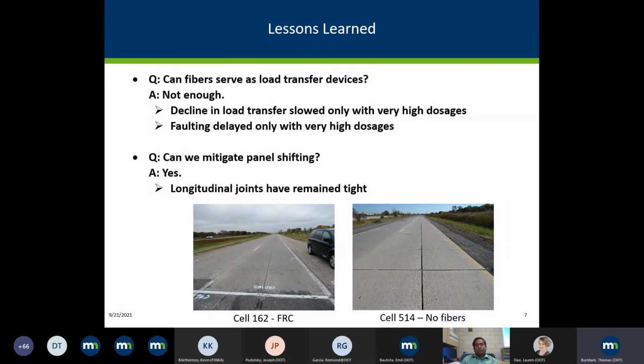Can fibers serve as load transfer devices? I would say not enough right now. We have seen at very high dosages, dosages so high that you start getting into placement issues, very difficult to finish the surface. Again, we did see it did delay, it did work for a while, but eventually it wears out. And same with the faulting, where we had no fibers, it was nearly immediate faulting going on. You put enough in there, it does have an effect, but again, is it practical to put that many fibers in?